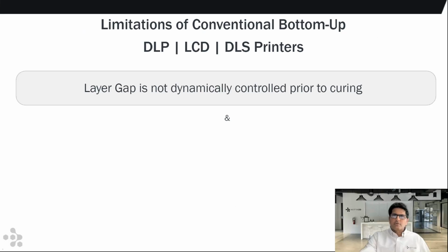The second aspect, which is the layer separation technology. Now let's look at moving to the projector-based systems. So now that we've covered the limitations of conventional SLA and we shift the focus to projector-based, fundamentally, there are two disadvantages on the way systems are today. One is there's a layer gap between the recently cured layer and the film, and there is no real good way to consistently maintain that gap to what is required. So if you need 100 microns, it's really never 100 microns. It's somewhere between 90 and 110, let's say, and you have to account through software on how to solve for that issue. The second is once the layer is cured, there is an issue.